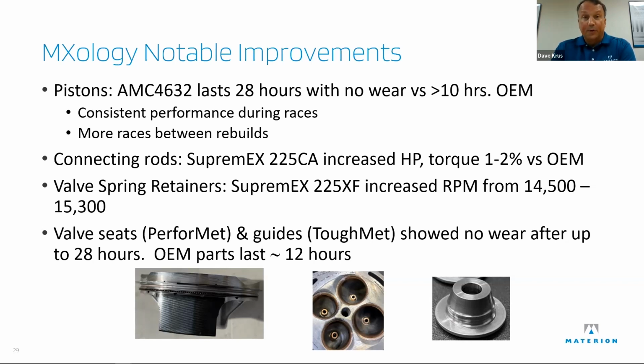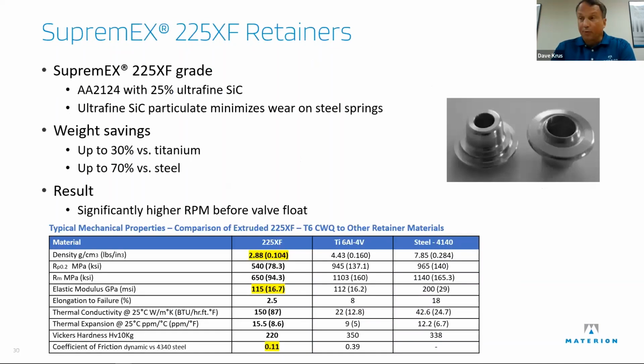To talk about the retainers, so the Supremex retainers, you'll notice that that's 225XF. That means extra fine. So the silicon carbide particles in 225CA are 3 microns. We found that at 3 microns, sometimes it scratches the top of the spring, which isn't a good thing. 225XF is 0.7 micron particle size, and that made the wear go away. So even finer, but it's still a 25% silicon carbide. You can make it 30% lighter than titanium, 70% lighter than steel.